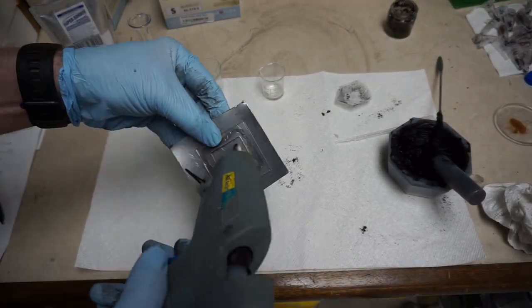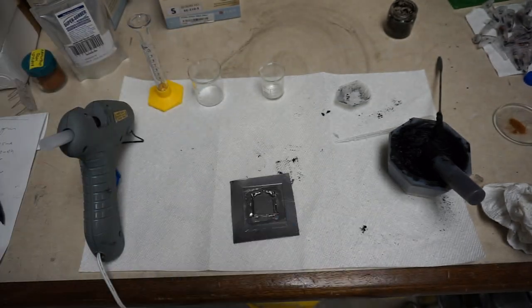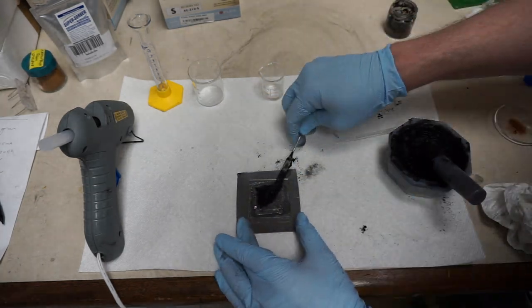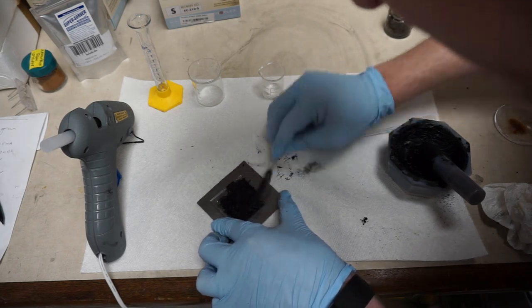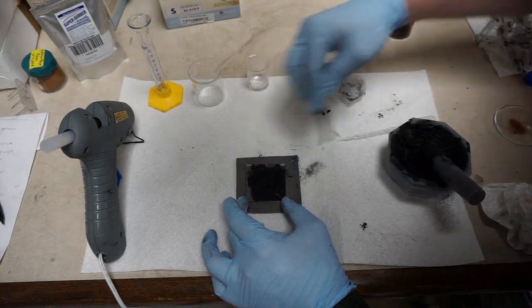I'm going to use this acrylic spacer. I'm going to seal the inside edge to avoid as much leakage as possible, and then I'm going to put finely divided iron wool, steel wool, into that chamber, and then pack the void space with that black carbon iron hydroxide paste.